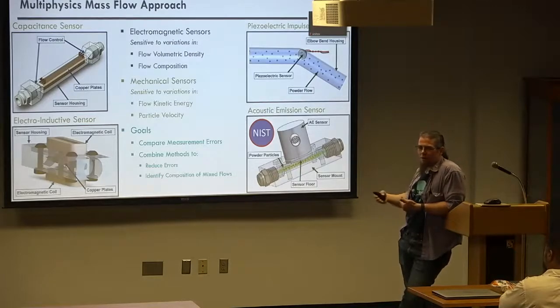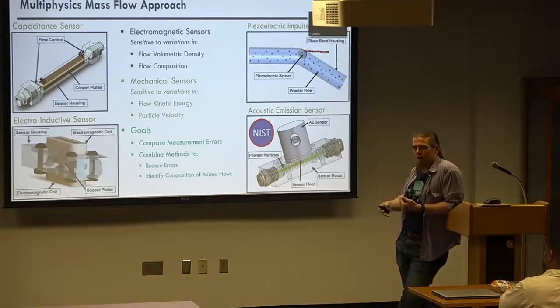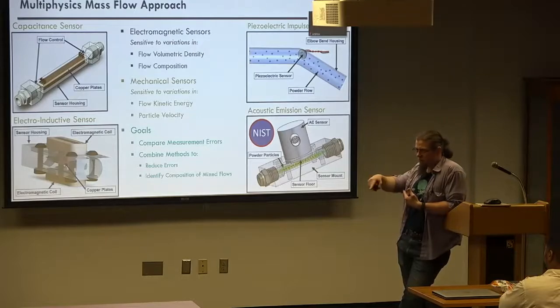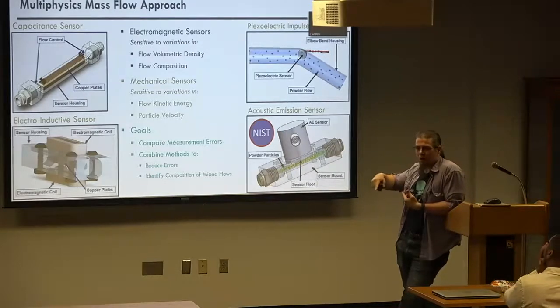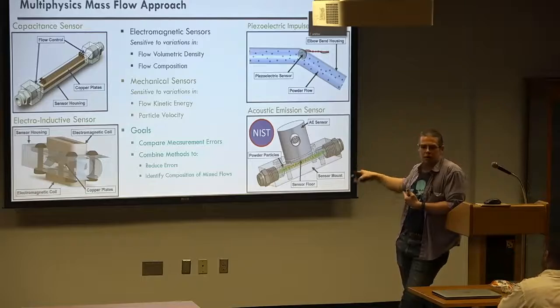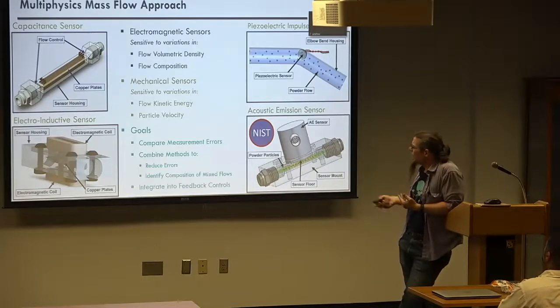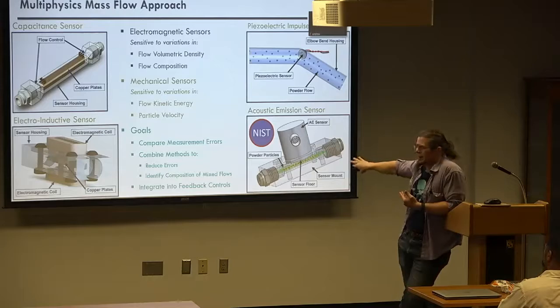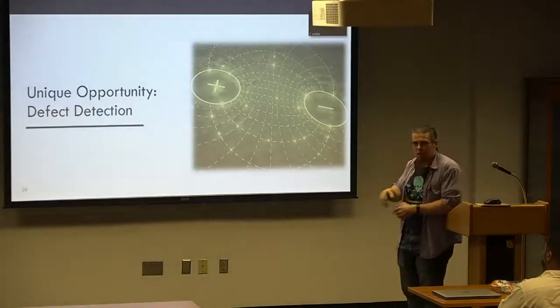We have 4 powder hoppers. We can mix them. I can put nickel in one, I can put titanium in the other, and I can flow them at different ratios to change that shape memory effect in what I'm printing. I want to do that reliably and have spatial variations across the part. I need to know what the composition of my flow is where I'm printing. So that's the next goal for this project. Once we can reduce errors in general mass flow, try and divide it up based on composition. And in all of these cases, integrate it back into some kind of feedback control system, so we can actually improve reliability of the system overall. So that was sort of the mass flow problem.